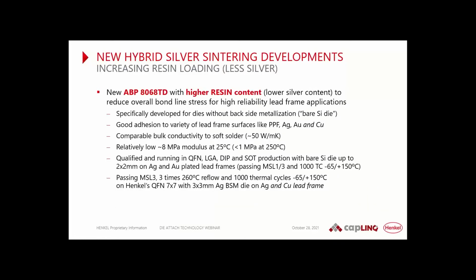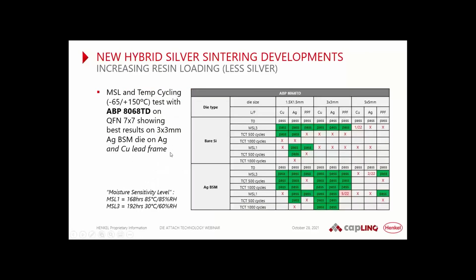To solve that die crack issue, we also went the other way around to increase the resin loading. In other words, less silver, so lower modulus. And I think this is our latest commercial material we launched. So basically then we compromise on the bulk conductivity, about 50 watt per meter Kelvin, but the modulus is going down a lot to about 8. And then if we do the MSL and temperature cycling tests on our internal test vehicle, then you see, let's say that material is passing up to 1,000 cycles on 3x3. Okay, it's still not the holy grail, but this is certainly good for expanding the application use.